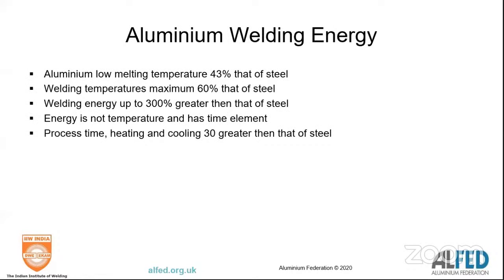So picking up on what we spoke so far, in essence, aluminium has a low melting point, typically about 40% that of steel. Welding temperatures are much, much lower than steel, never more than about 60% of that of steel. If you allow for the specific heat and the latent heat, typically you've got to put 300% more energy in than you would over steel, remembering that energy has a time element. And because of that time element, your process times are about 30% greater than that of steel. So more energy, greater times, very weldable. Okay.